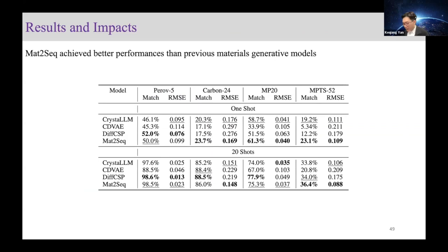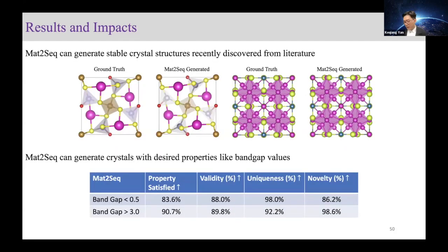So here I show some comparisons with other generative AI in material science, like the crystal language model that uses CIF files, or CDVAE and DiffCSP that are diffusion-based models specifically designed for material discovery. We achieved significant performance gains beyond these methods, even beyond diffusion models specifically designed for materials. And as we can see here, the method can actually rediscover recently experimentally found stable structures with high alignment. And we also verify that our method can generate crystals with desired properties like high bandgap value and low bandgap value with high success rate and uniqueness, validity, and novelty.